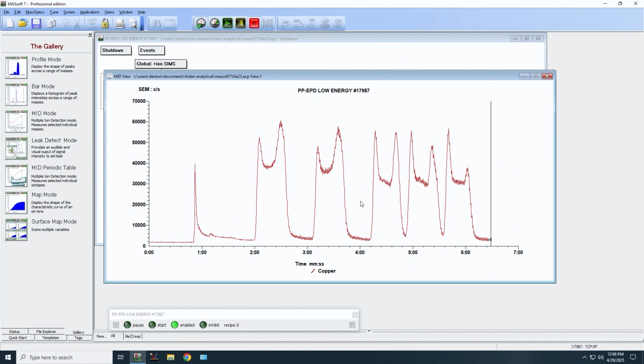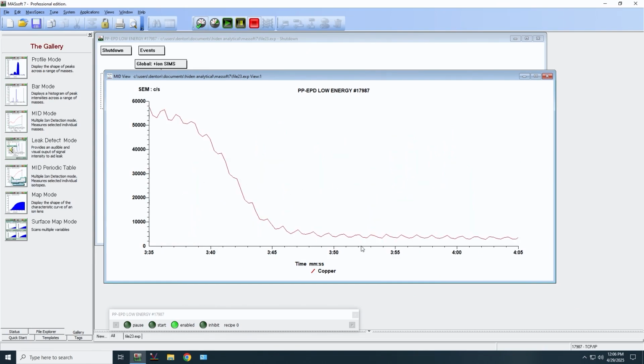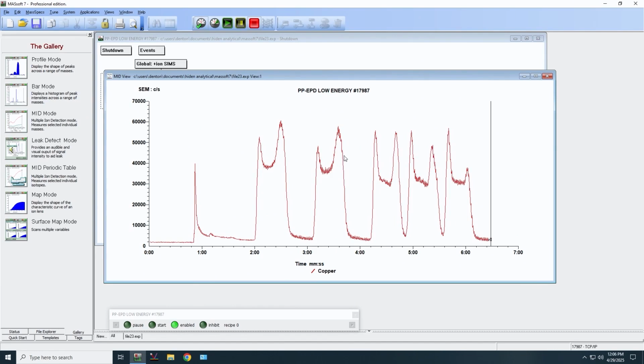And then I want to be somewhere in the middle of the via layer. So let's say I want to end right at 4 minutes, which is in the middle. In between this point, which is 30,000 counts, at 3 minutes and 42 seconds, and 4 minutes, that gives me 18 seconds. So I'm going to tell it to look for the second falling edge and then wait an additional 18 seconds. Then this SIMS controller is going to flip an input on the PLC and etching will stop immediately. It will turn off the source and close the shutter.